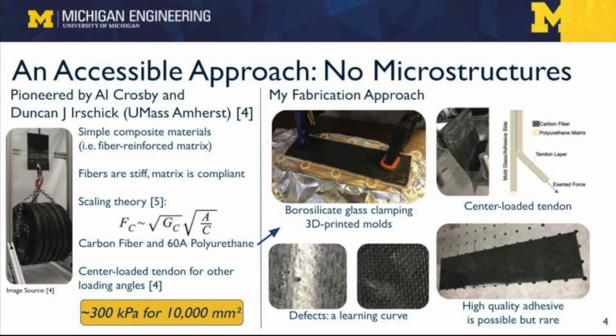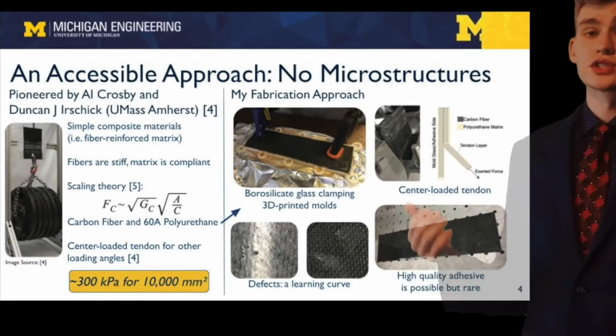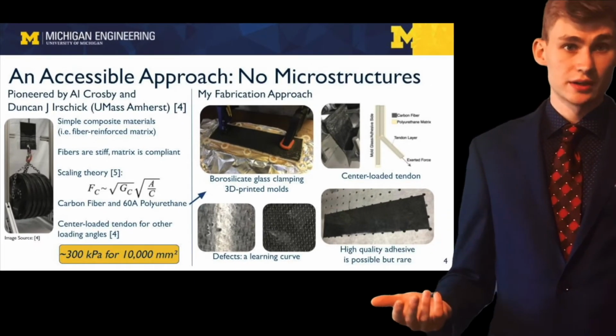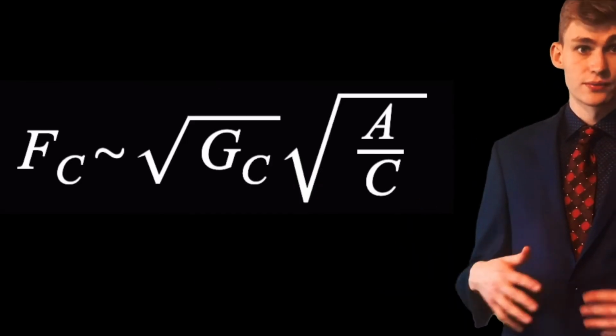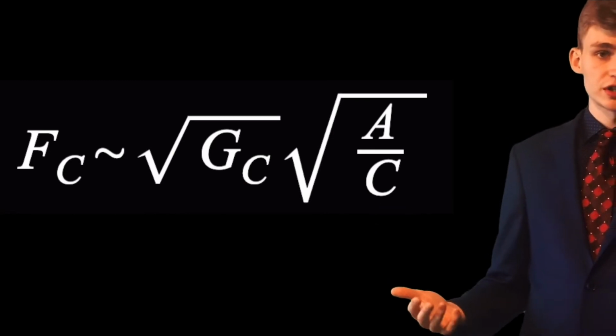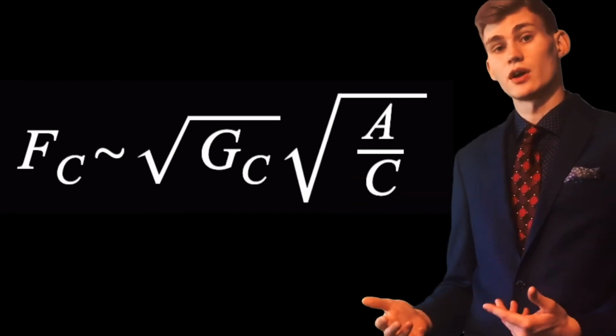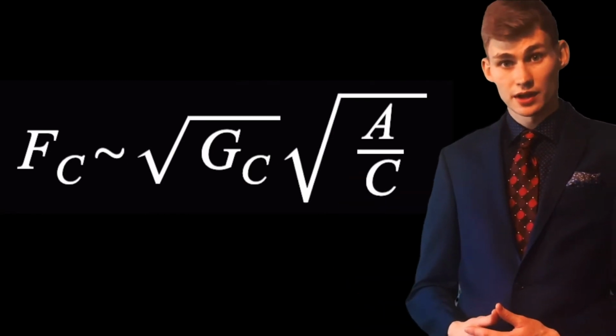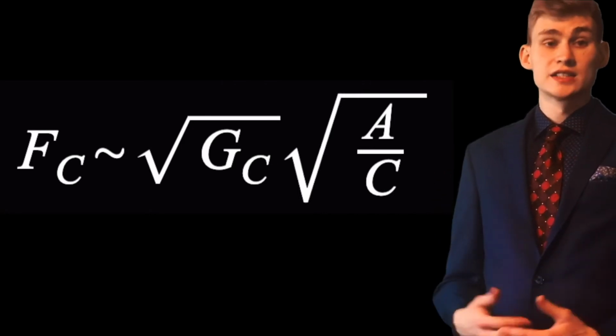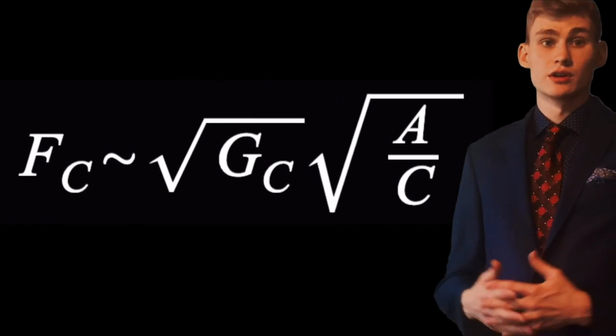The stiff fibers serve to decrease the compliance, or increase the stiffness, parallel to the surface to give the strength that the adhesive needs to support large loads. This is much similar to the way geckos have a stiff tendon woven directly from their setae into their skeleton. From this approach, the researchers also developed a scaling theory that the adhesive's critical load, the force capacity, will scale proportionally with the quantity of the square root of the area divided by the compliance, where the compliance in this case is measured in shear, parallel to the surface.